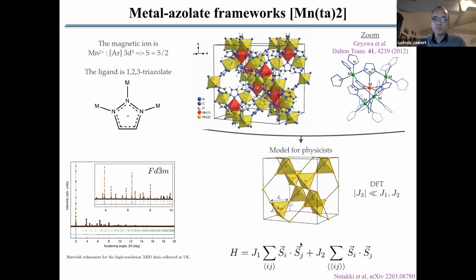And so that's why the Hamiltonian we're going to consider is this centered pyrochlore lattice with J1 interactions between the center spin and the corner spins, and J2 interactions between the corner spins. So here, if it was just J2, it would be a pyrochlore lattice. If it was just J1, it would be a decorated diamond lattice. But with J1 and J2, we have this strongly frustrated geometry that we're going to study now.